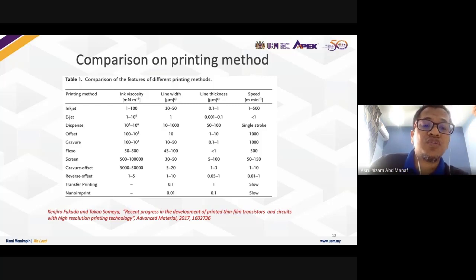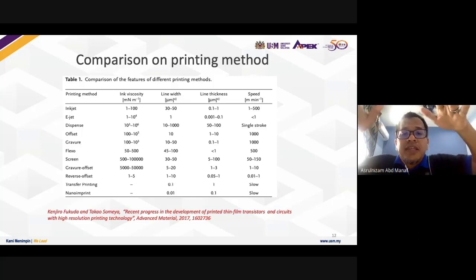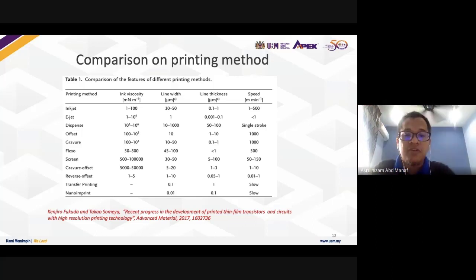So how we choose the ink criteria: ink viscosity, of course the line width, the line thickness, and also the uniformity. Normally when the ink comes out, it will start to cure from the center to the edge. From the center to the edge. So there is some non-uniformity between the center and the edge, right?